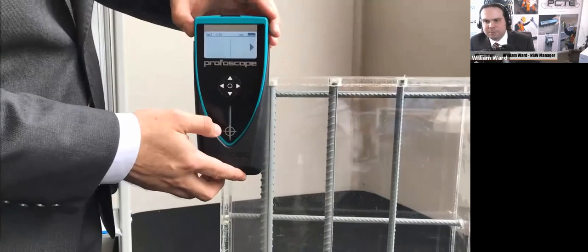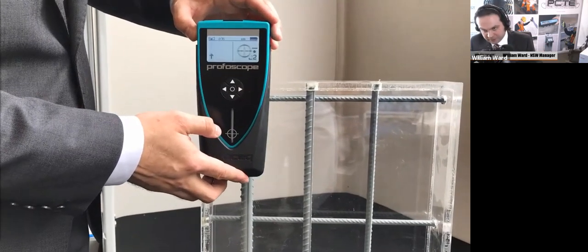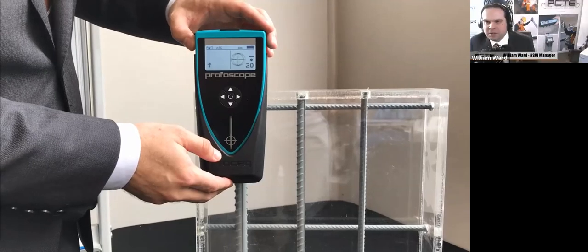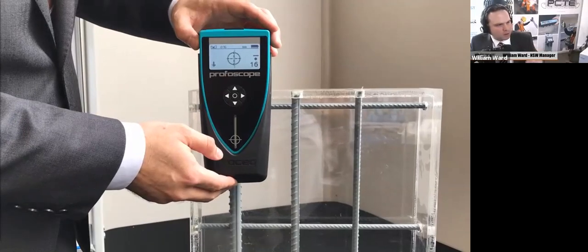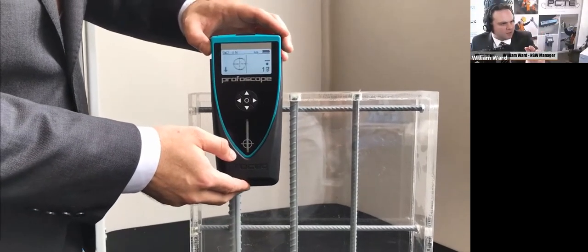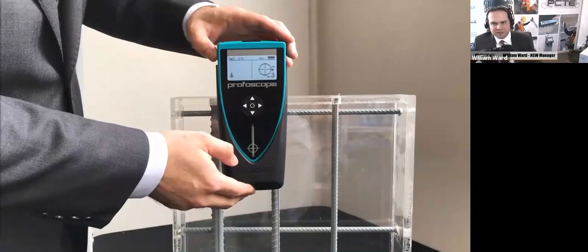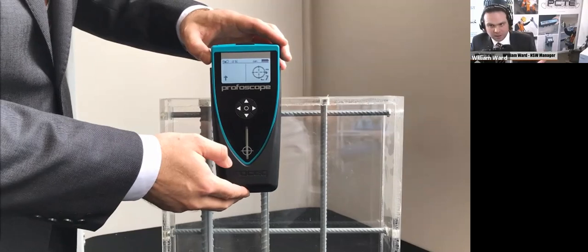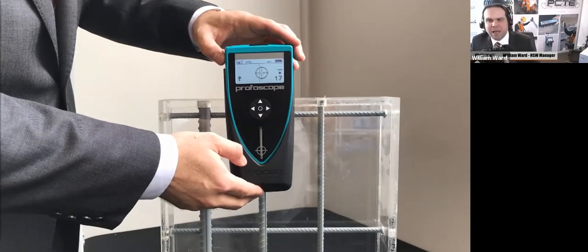Now, this particular video is just showing a past version of myself looking at just the basic procedure for measuring depth to reinforcing steel. Now, there's slightly different reinforcing bar sizes here too, but you can see that I'm sliding my cover meter from the side over to my measurement point. That's the first critical thing to do with cover meter probes. You don't place them on the surface and read the number off. You will possibly not be over the top of a reinforcing bar. Whereas if you slide your cover meter, you're going to approach the center points of the bar as we're coming to now, be able to quickly nab the middle and read off the cover depth. In that case, that was 70 mils cover depth.